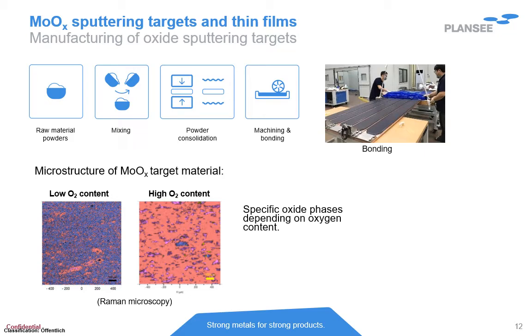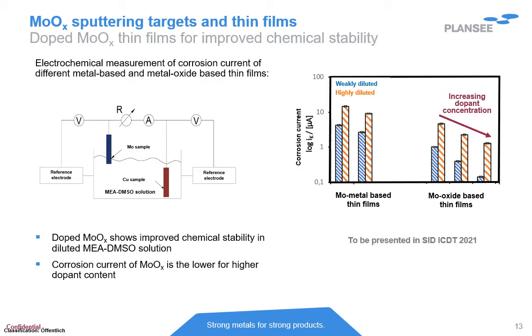An important factor for using those molybdenum oxide thin films is the chemical stability. That chemical stability depends on the oxygen content. And a very interesting thing is that you can improve that chemical stability for different water-based or non-water-based solutions by adding dopants into the molybdenum oxide. Those dopants can be, for example, other metals. It can be other oxides that you can mix or bring into the microstructure of that material. This can be measured in an electrochemical cell, and you clearly see here on this slide that by adding different dopants, the chemical stability, explained by the corrosion current, can be strongly improved for several molybdenum oxides.